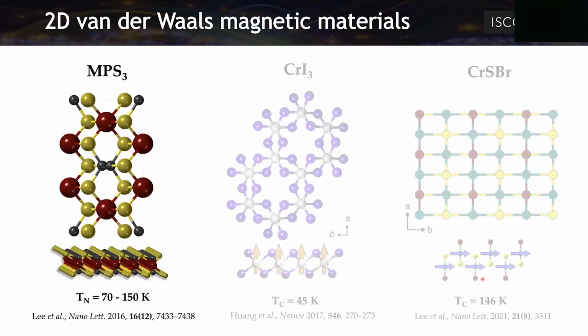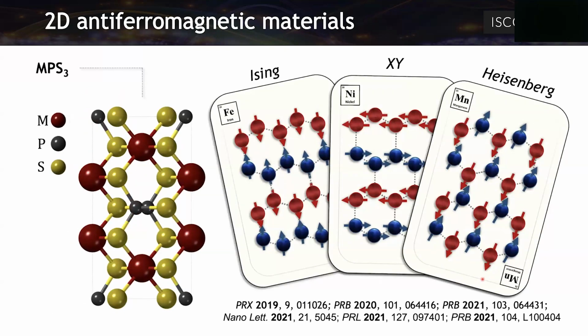Then regarding the transition metal phosphorus trichalcogenides, one thing that is really interesting in this material is that depending on the transition metal, we can have different magnetic orders. All of them are 2D antiferromagnets, but in the case of iron, we have spins out of plane following these zigzag chains. In the case of nickel, they are also zigzag, but the spins are in plane. And in the case of manganese, we have Néel magnetism, so all the interactions are antiferromagnetic. These studies are relevant because they have been also measuring and creating magnons in this material. And with antiferromagnets, in principle, we can go up to terahertz frequencies.